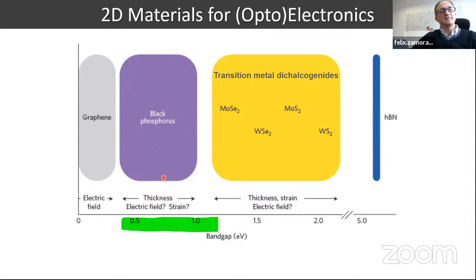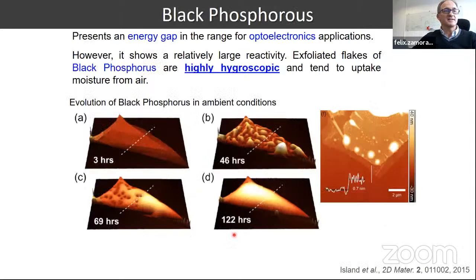But the question with black phosphorus is this, nicely represented by the work of Andrés Castellanos, in which they show that when you isolate black phosphorus on top of some substrate, here I think it was silicon oxide, the nanolayers of black phosphorus show degradation over time under ambient conditions, because of oxidation and hydrolysis of this starting material. So from this point of view, black phosphorus shows difficulties in providing a material able to form 2D devices.